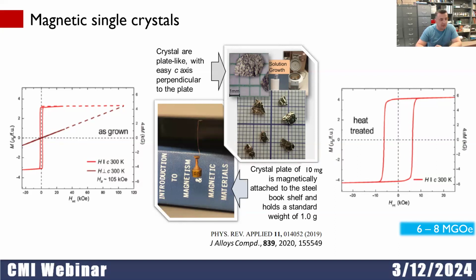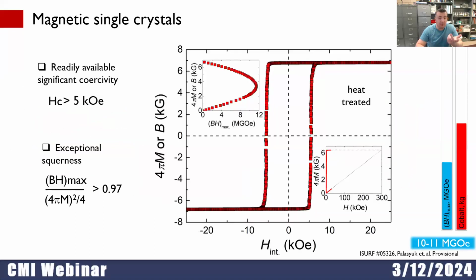And for example, in the central figure, you see 10 milligrams of single crystal plate is holding 1 gram of the weight. So it's a very interesting phenomenon where you have extrinsic characteristics appear readily after the heat treatment. And we developed it, in fact, and we reached in single crystals, in nominal single crystals, if you wish, because you will see later that these are not single crystals anymore. So we reached 10 to 11 megagauss-oersted. We diluted cobalt already with some other elements, and price to performance of this material starts to be attractive.